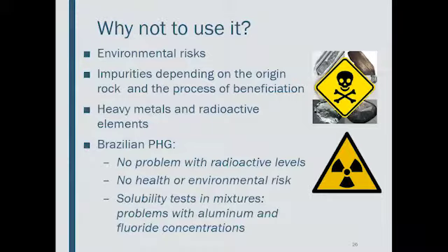You can use this material for engineering purposes, but you have to take care about the environmental risks because of the impurities that can appear, depending on the origin rock and the beneficiation process that happens in the industry. So you can find heavy metals and radioactive elements in this material. In the case of the Brazilian phosphogypsum, we observed no problem with radioactive levels and no health or environmental risk. But some solubility tests showed problems with aluminum and fluoride concentrations.